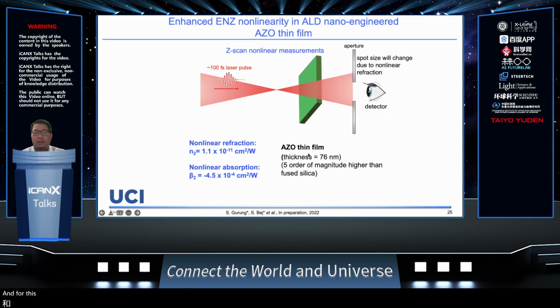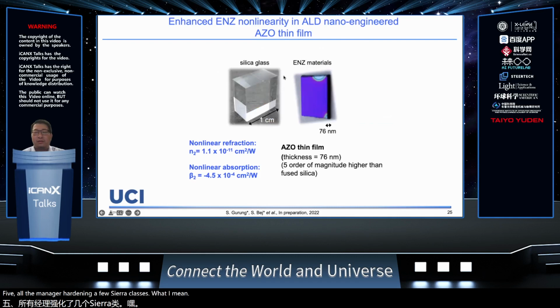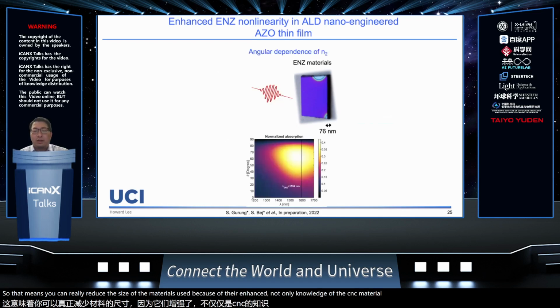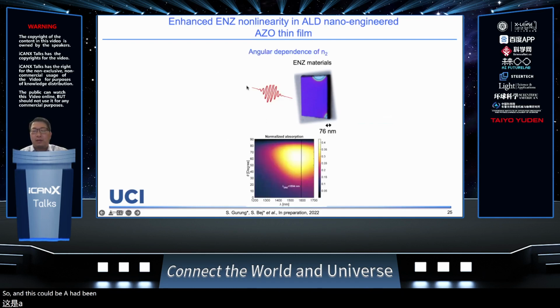I try to simplify here, but just to show you the result. For this sample of AZO with 76 nanometer, the nonlinearity is already 5 orders of magnitude higher than silica glass. What I mean is that if you have 1 centimeter of silica glass, in order to control the phase using a laser pulse, you only need around 100 nanometer of this ENZ material to obtain a similar optical phase change using the same power pulse. So that means you can really reduce the size of the material you use because of the enhanced nonlinearity of this ENZ material.